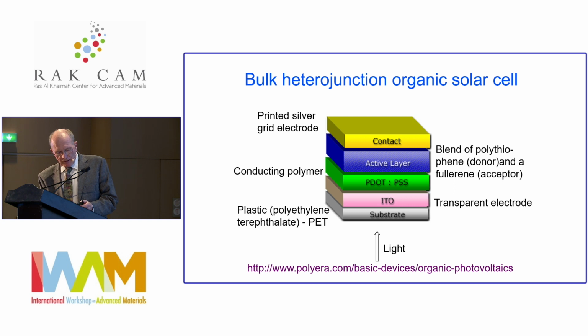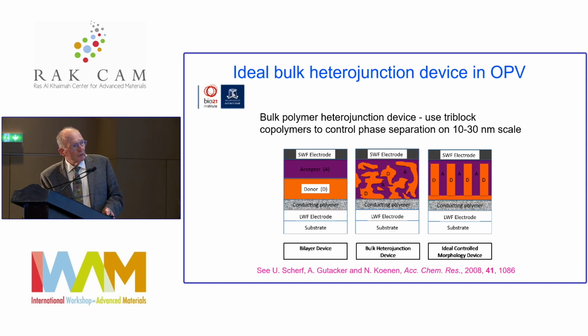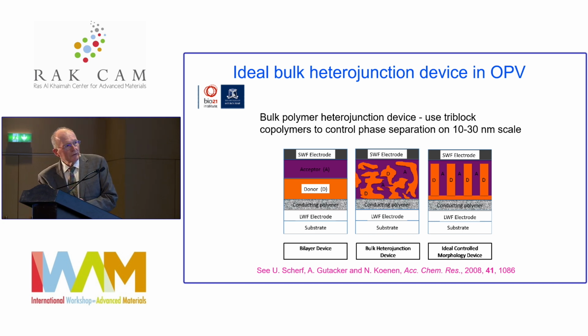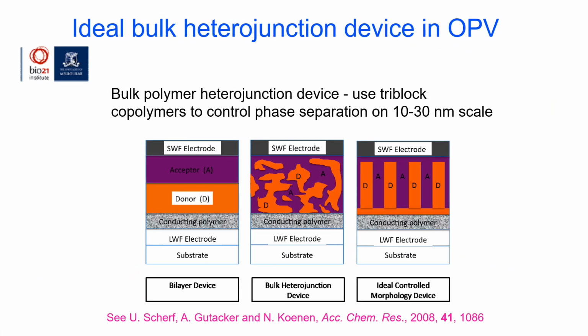And I want to talk just briefly about our contribution in a solar cell consortium in the state of Victoria in Australia, where we set ourselves a target of delivering a 10% efficiency, and that was ambitious at the time for these materials. And the problem is that the devices depend on interfaces, because it's at the interface that the excited state, the excitonic state, resulting from the absorption of a photon, separates into the positive and negative charges. And that needs assistance with a barrier, or barrier is the wrong word, with a break where the charges can separate. So the donor-acceptor interface is where the exciton separates into positive and negative charges, and they don't survive very long in most organic materials until that happens.